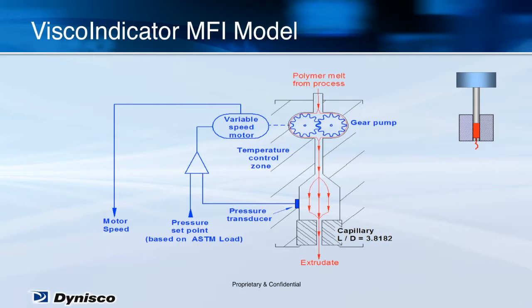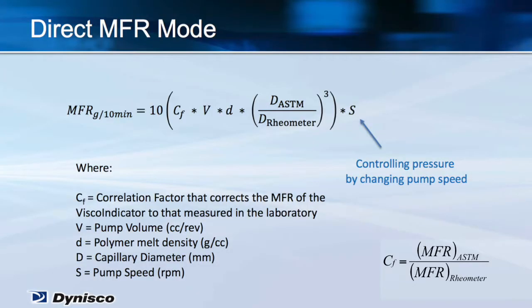If you don't know the melt density for your polymer, you can easily measure it using a standard method on a melt flow indexer. This is how a visco indicator duplicates the test result from a melt flow indexer right on the extruder without needing a technician. Although the machine can control pump speed, enabling shear rate control, allowing viscosity measurements, we're going to talk about melt flow index testing. In direct MFR mode, pressure is controlled to the level that is equivalent to the weight used during the lab test. The pump speed required to maintain this pressure is the only variable in the equation that changes in real time, as you can see on the slide.